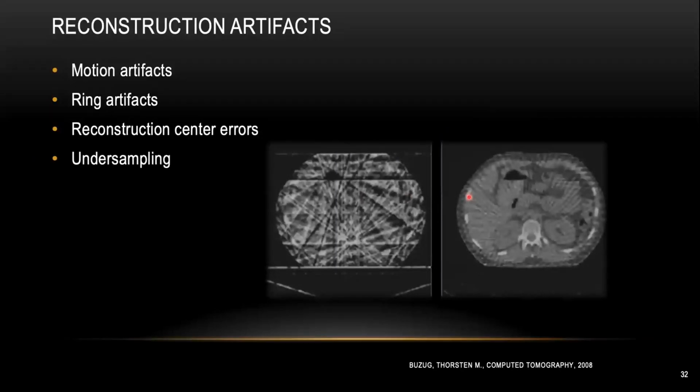And earlier I already mentioned, the more projection images, the better your reconstructed result. So here is a comparison of two different images. The image is a medical CT image, but with a different number of projections. You can see with a higher number of projection images, now we can see much greater detail inside your sample. With a low number of projection images, we just call it an undersampling issue.